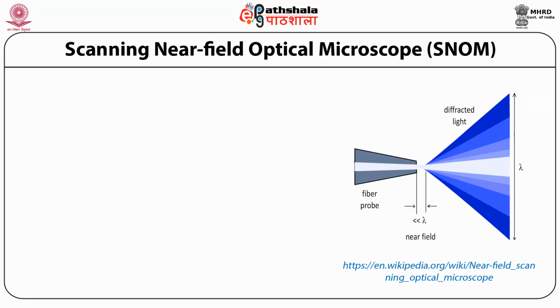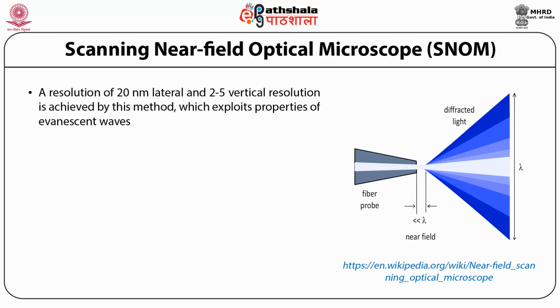This microscopy allows very high resolution, 20 nanometer lateral as well as 2-5 vertical resolution. This is based upon the fact that this microscopy exploits the evanescent wave nature, and evanescent waves are actually oscillating magnetic fields which do not propagate. So if an evanescent wave is generated on the sample or within the sample, it will oscillate there, and the energy within that confined area can be used to generate a high resolution image of our sample.